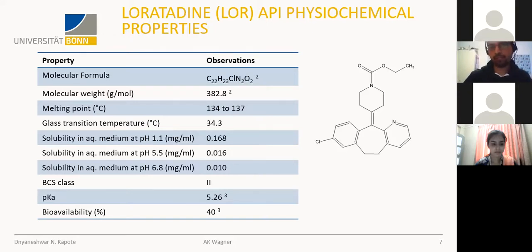So we need to address this problem, and that's why we did some physicochemical characterization, where the melting point observed was 134 degrees Celsius and the glass transition temperature was 34.3 degrees Celsius, making it an excellent candidate for hot melt extrusion as well as spray drying.